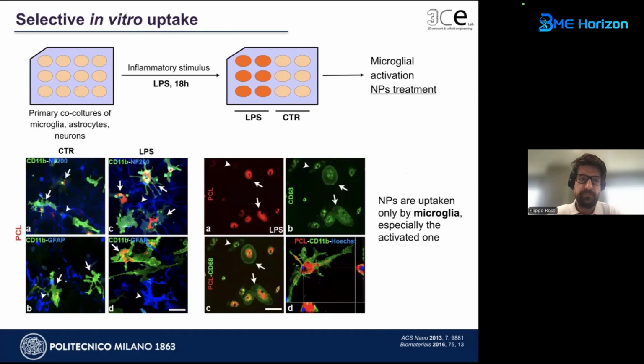Then we added this nanoparticle to primary cultures of microglia, astrocytes, and neurons. We introduced a pro-inflammatory stimulus, lipopolysaccharide, for 18 hours, and then we added the nanoparticle. We can see from the confocal picture that the nanoparticles, in red because they are post-polymer functionalized with rhodamine, are present only within microglia; as you can see from the picture here, they are uptaken only by microglia, especially the activated ones. This is extremely clear from confocal picture D on the bottom right, where you can see in green the membrane, in blue the nucleus of these cells, and in red all the nanoparticles uptaken.